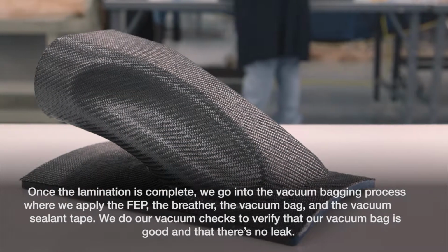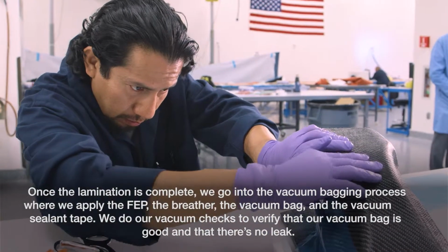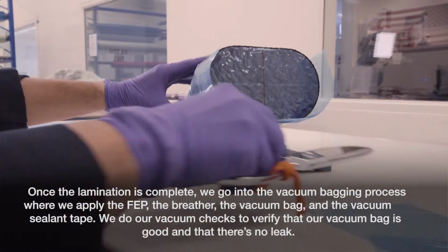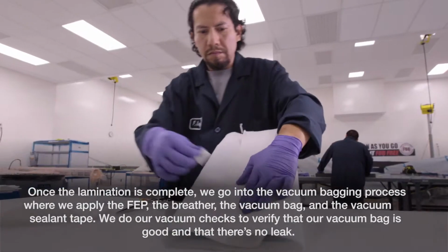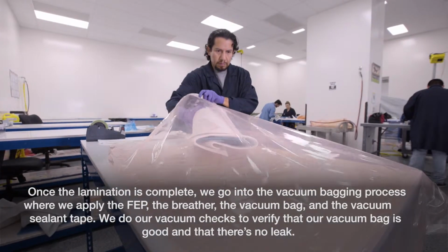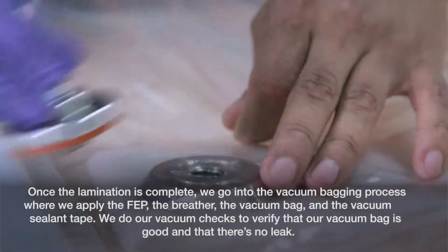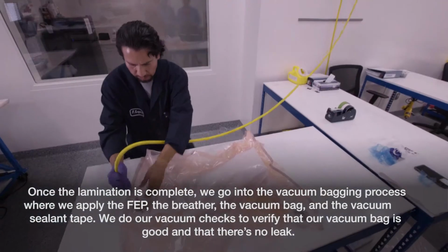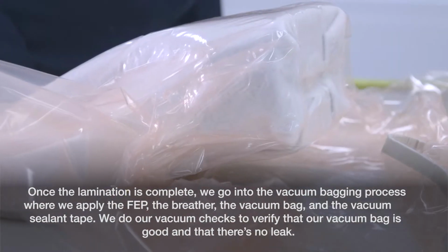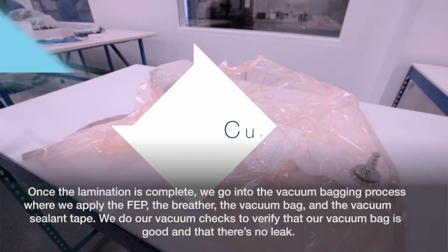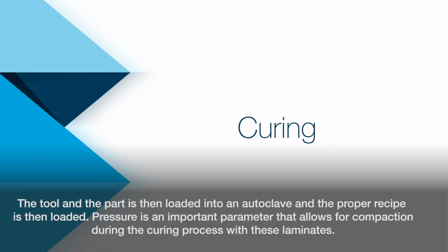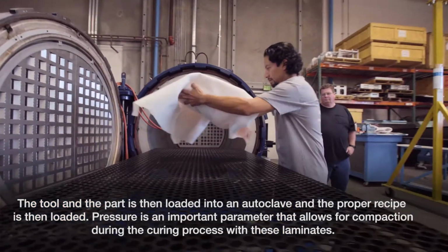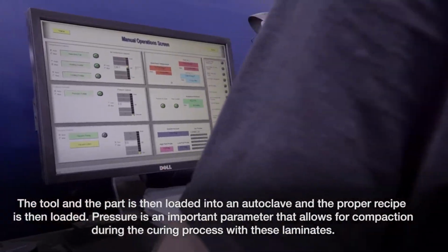Once the lamination is complete, we go into the vacuum bagging process where we apply the FEP, the breather, the vacuum bag, and the vacuum sealant tape. We do our vacuum checks to verify that our vacuum bag is good and that there's no leak. The tool and the part is then loaded into an autoclave and the proper recipe is then loaded.